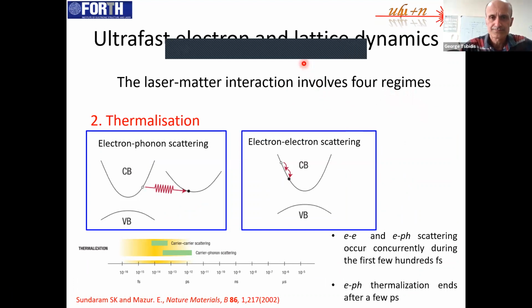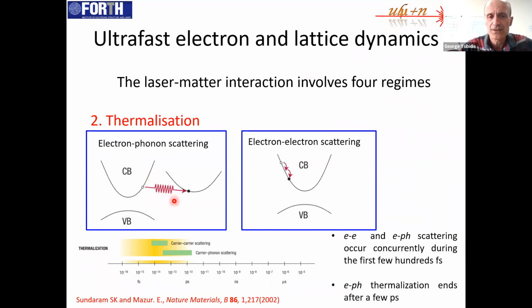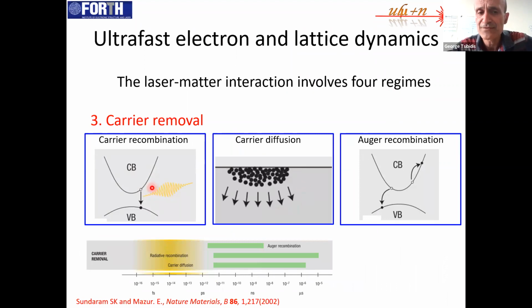Then we have the thermalization regime, when we have the electron-phonon scattering, as I said. And then we can have a third regime, the so-called carrier removal. The electron in the conduction band can lose energy, and then through a radiative process, it can fall to the valence band, or the electrons can lose energy through diffusion inside bigger depths, or another process which is called Auger recombination,